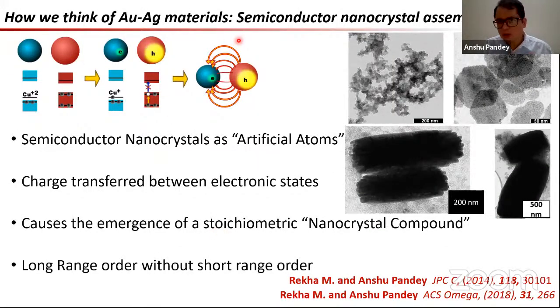So the thing which I would like to draw your attention to very quickly would be the work on semiconductor nanocrystals, which we had done a while back. And this was indeed the analogy with which we had started working in this family of materials. What we were trying at that time was simply to have a charge transfer initiated between 2 different varieties of nanocrystals, in such a way that the charge is transferred from one electronic state to another electronic state. What happens apparently in these conditions is that after the electron is transferred, the nanocrystals build up a Coulomb interaction and then sort of pull each other together and crash out of solution.